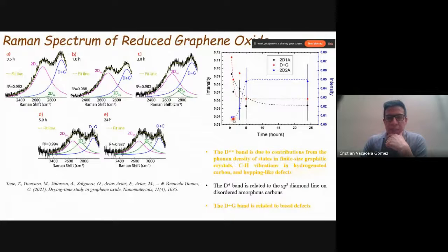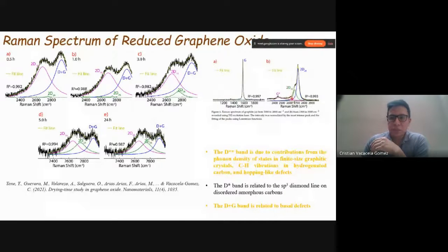in the 2D2A band here, this is represented in blue color, it starts to increase. Yeah, so it starts to increase. For example, here is a lower intensity, increase the intensity, more intensity in here. Of course, maybe our hypothesis is that it could increase even more, for example for 84 hours, 7 days, I don't know. We didn't try extending the reduction time further to see if it is possible to get something like this structure. The idea, in theory, is that we expect that by increasing the reduction time, we will observe something like this.